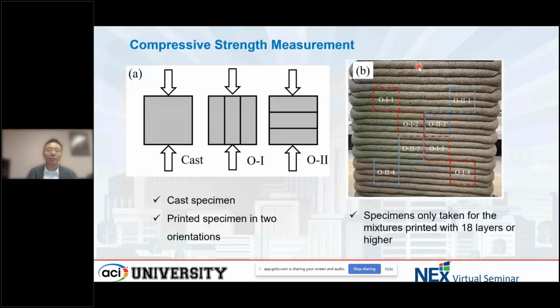So now I'm going to the strength section. We measure the compressive strength of a mixture with the sample cast in the mold, and we also cut the printed filament, as shown in figure B here, and we measure the compressive strength of the sample in two orientations. For example, orientation 1 is like this, the bond layer is here, and orientation 2 is like this, the bond layer is horizontal.